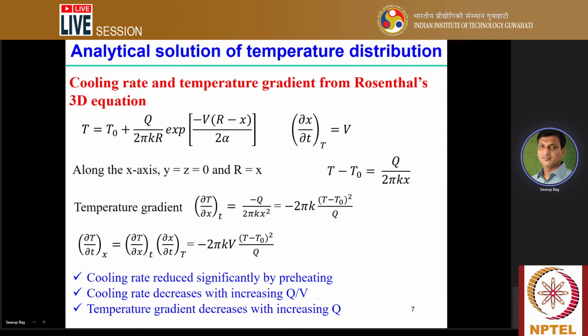Now, what inferences can we conclude from this particular expression? We can see that cooling rate is reduced significantly by preheating. T0 is the reference temperature, or maybe the initial temperature, or maybe the preheating temperature of the particular sample. When we start with the solution, we start from one initial temperature, say in a welding process performed at ambient temperature. So the initial temperature was the ambient. Now if it is preheated, you have already raised the temperature, and from there you apply the heat flux and get the solution of the temperature.